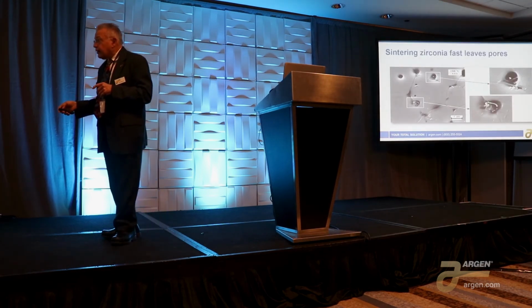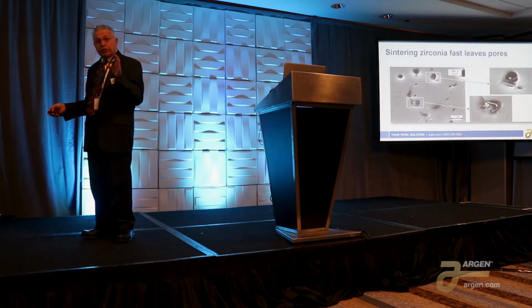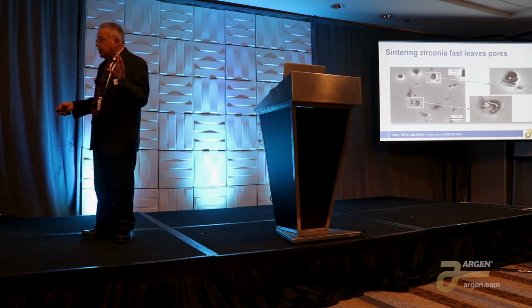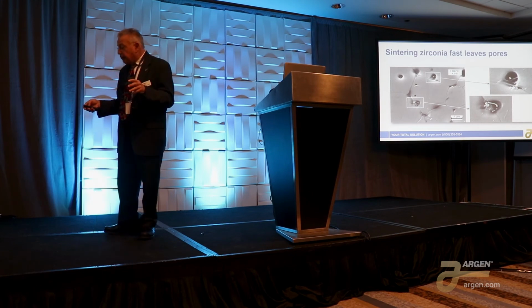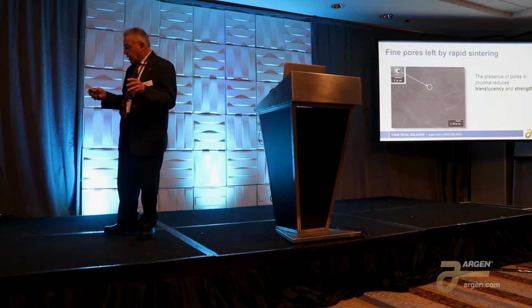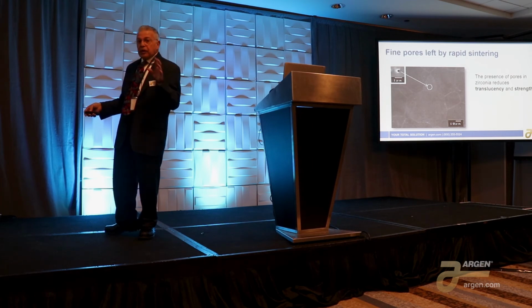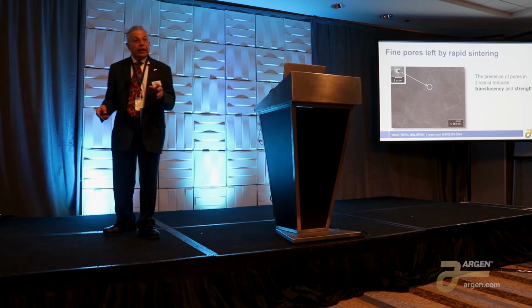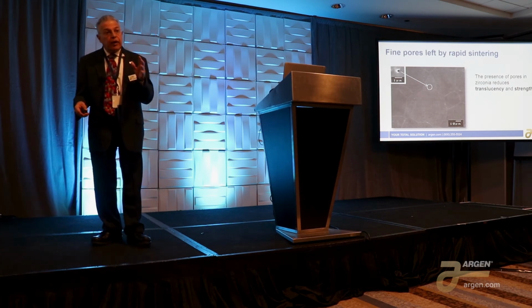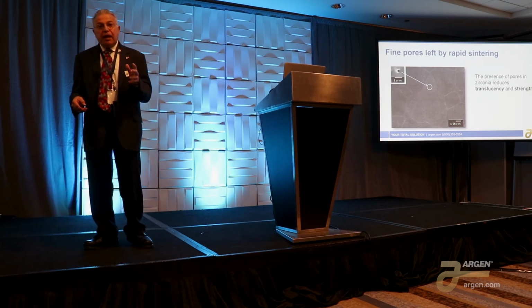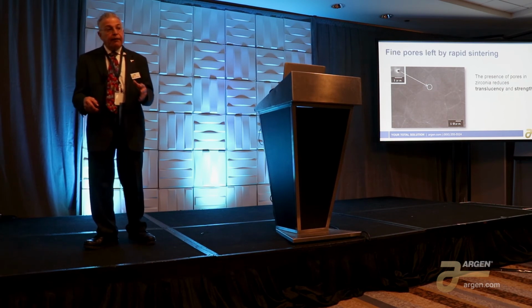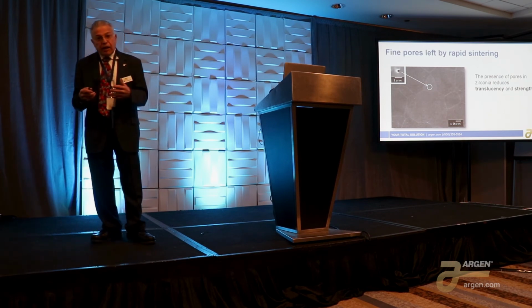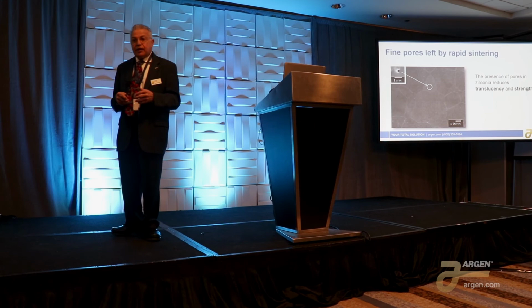Now, as I said, the only way the gas is going to get out of there is through the grain boundaries. If you try and sinter it too fast, you're going to leave some gas behind. And what happens, even if you're trying to do a really good job, you're going to leave some pores behind, and those are going to refract the light. So that means that your zirconia is not going to be as translucent as you expect it to be. Okay? If you go too fast, it's not going to be as translucent as you like.